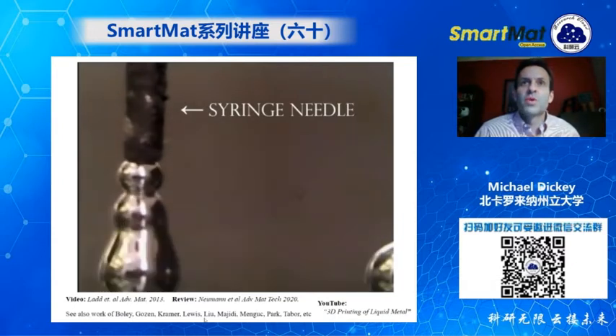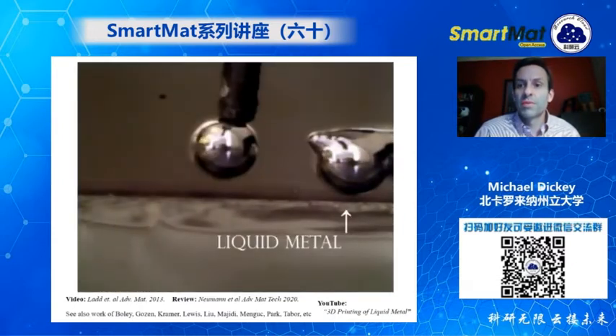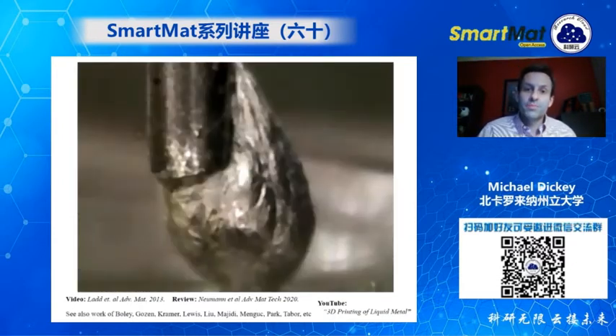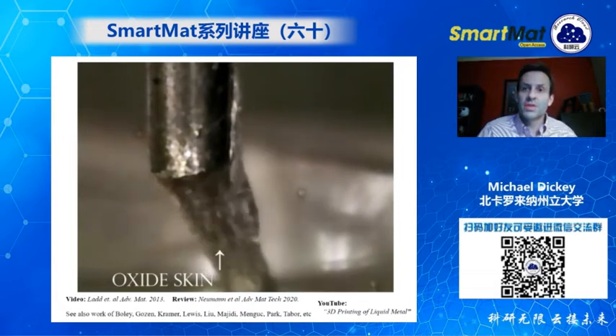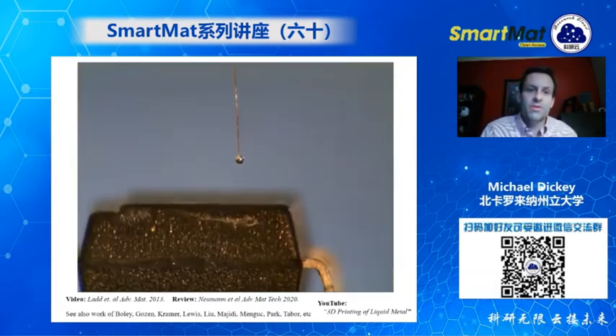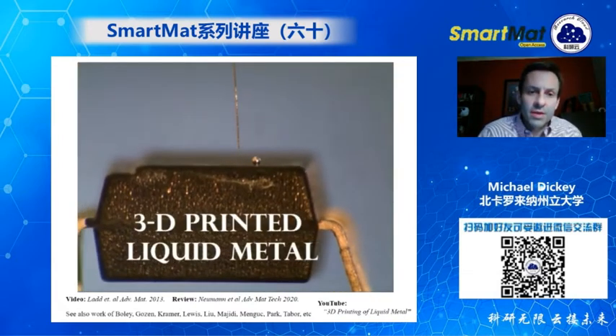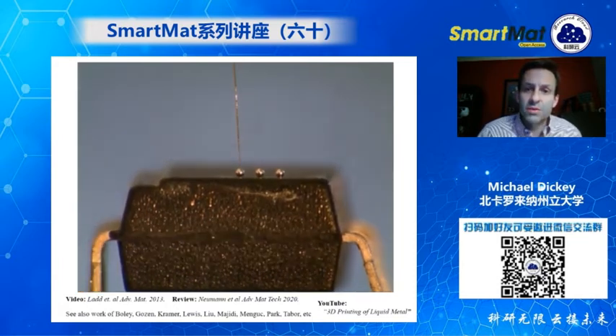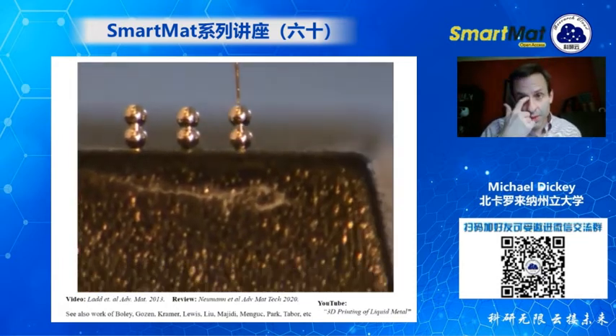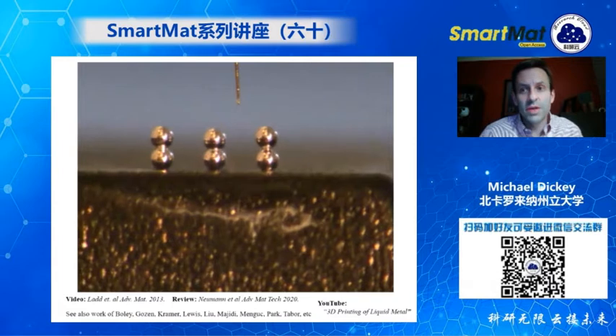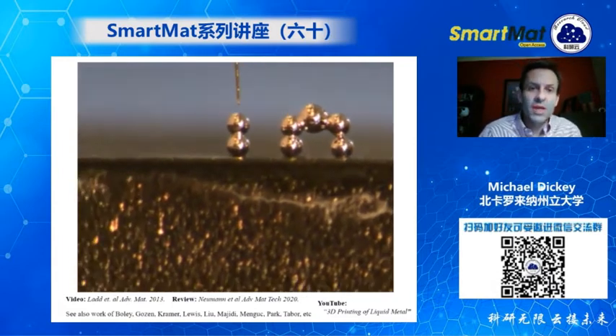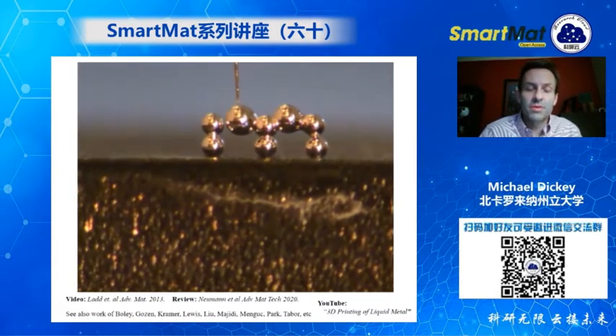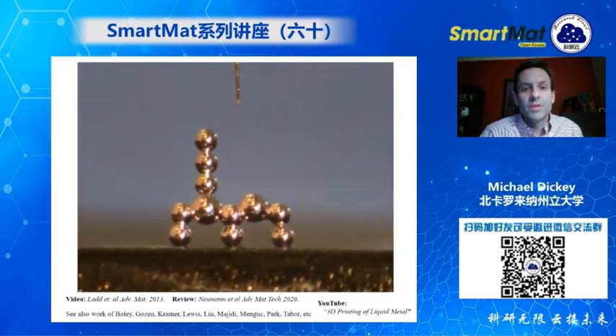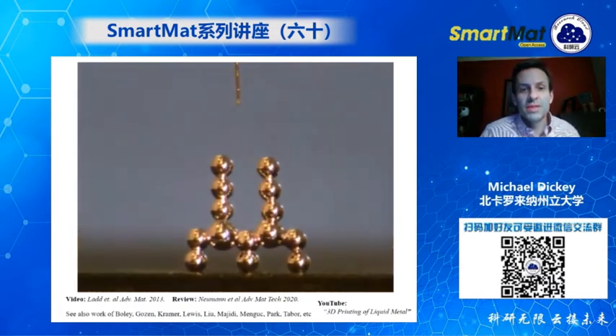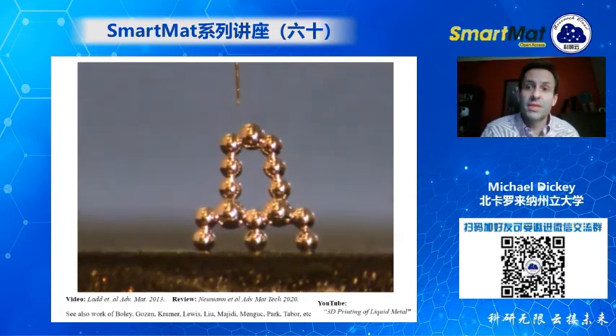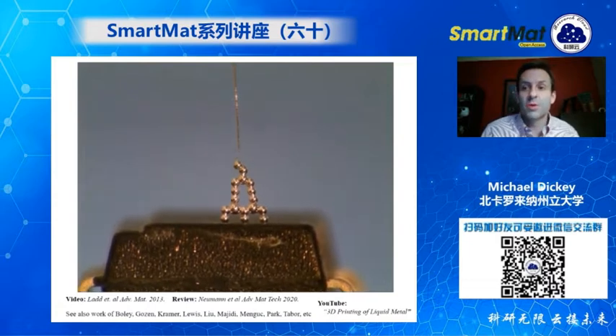So to drive home this point, this is a video of the ability to 3D print liquid metal. And if you take the metal and you suck it back into the syringe, you can see the oxide sort of wrinkle. And this oxide layer forms so fast and is so strong that you can actually 3D print this material at room temperature. So for the first time, you can truly print metals at room temperature. And so this, again, is liquid the whole time, and it's held together entirely by this very thin oxide layer that forms spontaneously.